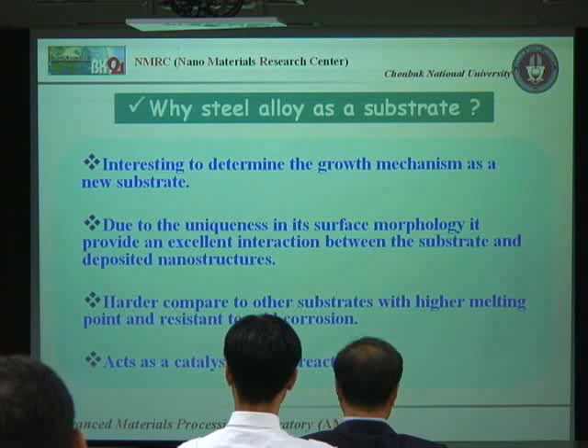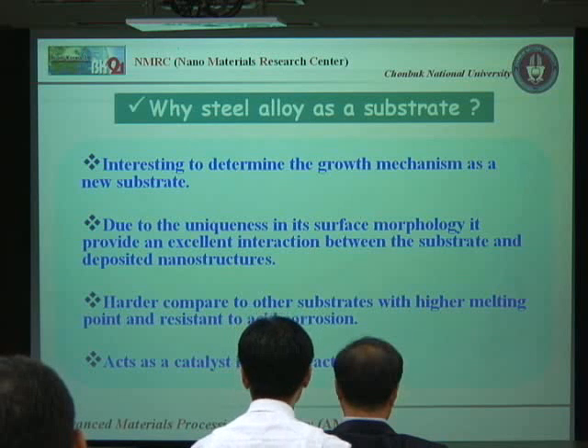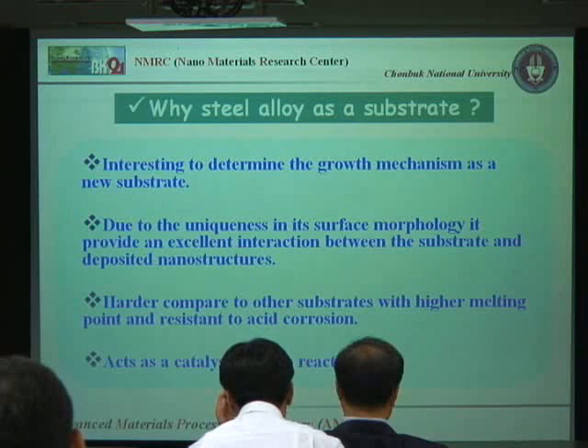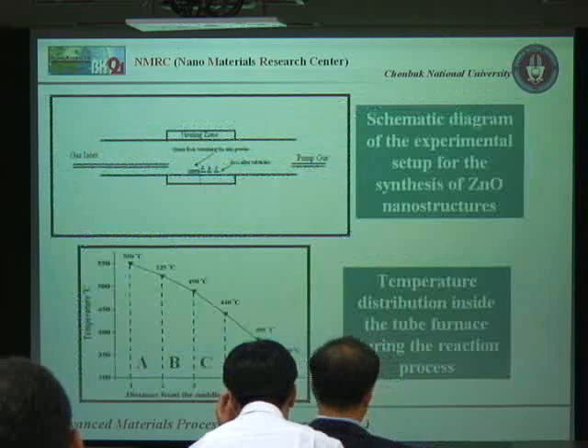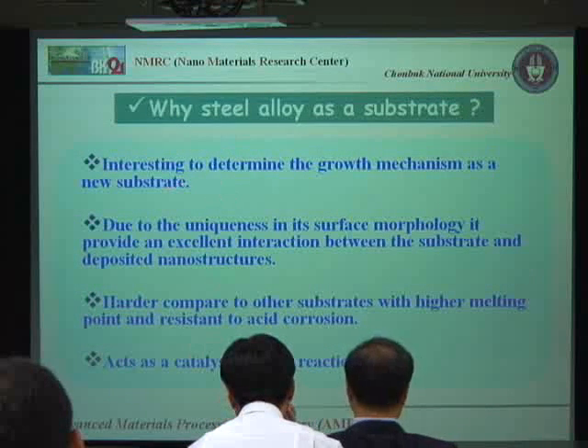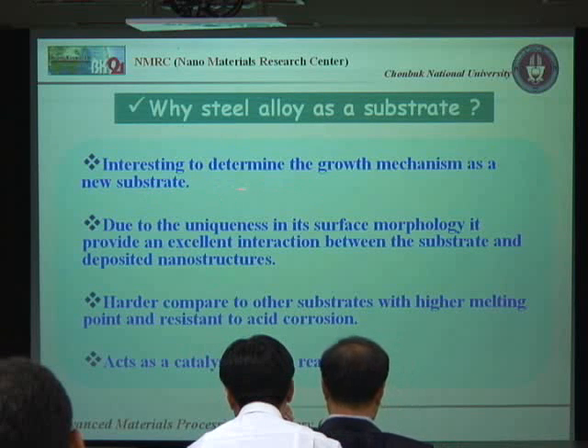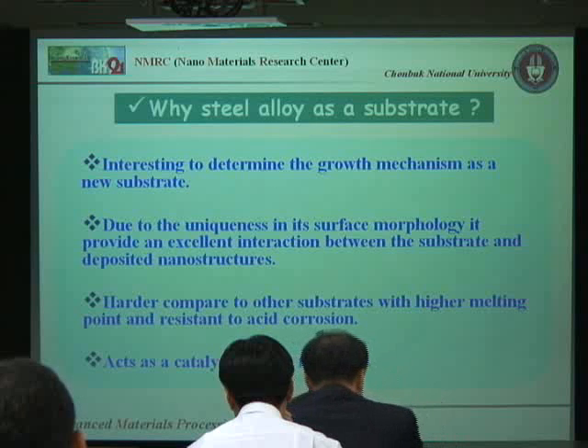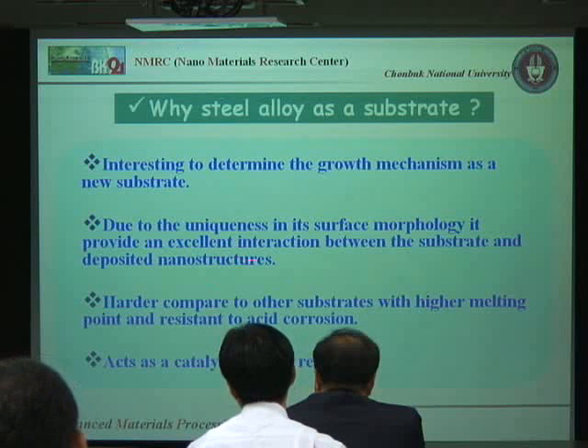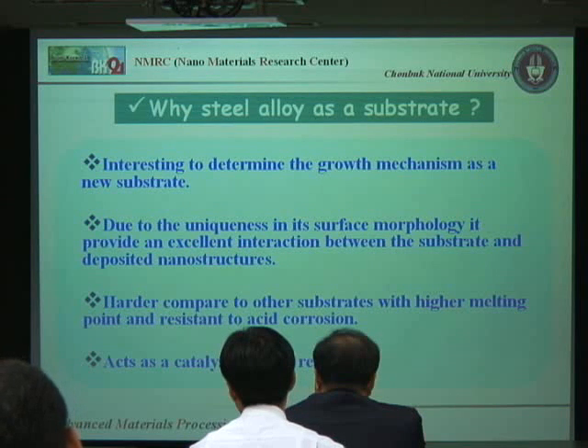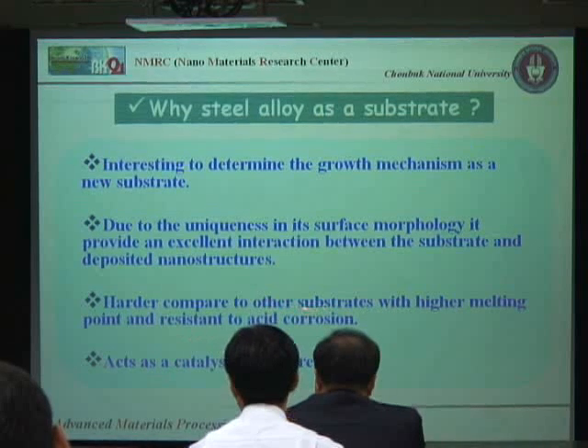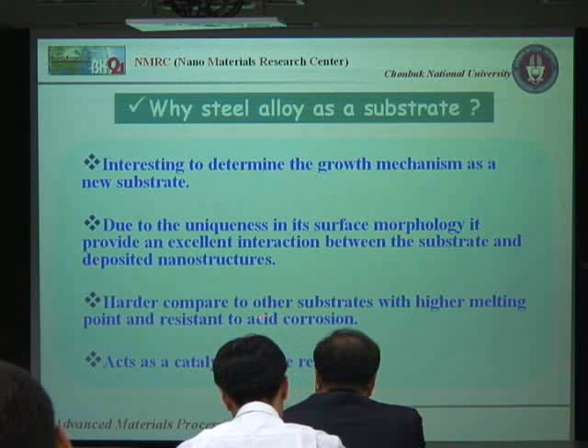Among common substrates, we use a different substrate in the synthesis, the steel alloy. We choose this substrate because of some interesting phenomena of this substrate. In some cases, this substrate can be used as a catalyst, and because of this, it's very interesting to determine its growth mechanism. The surface morphology of this steel alloy substrate is rough, which provides an excellent interaction between the substrate and the deposited materials. And this is a harder substrate compared to other substrates, with a higher melting point and resistant to acid corrosion.